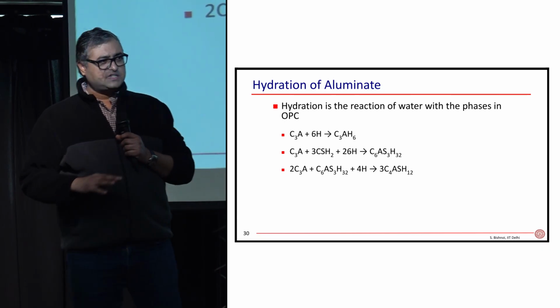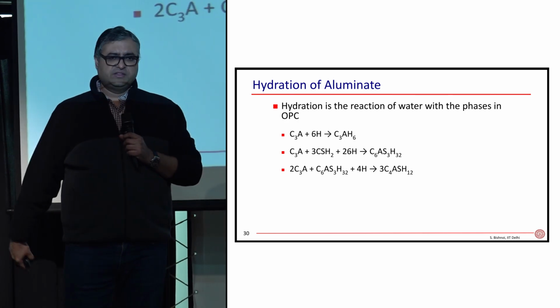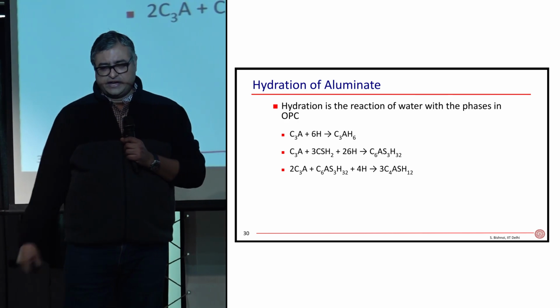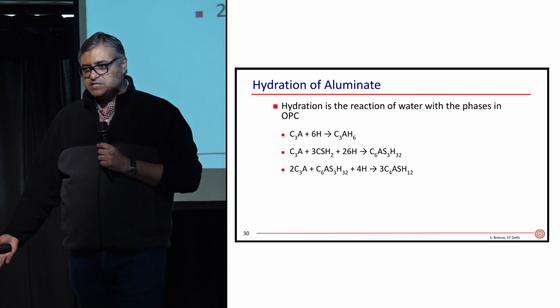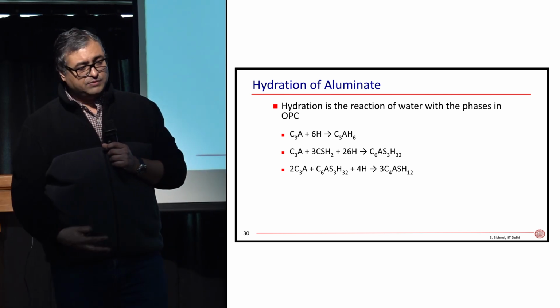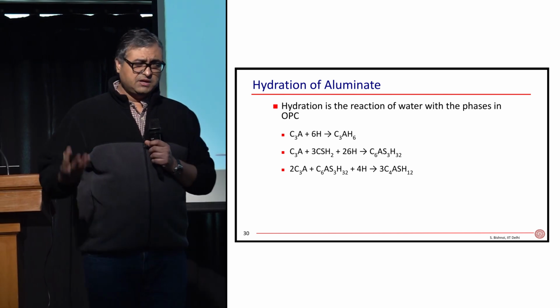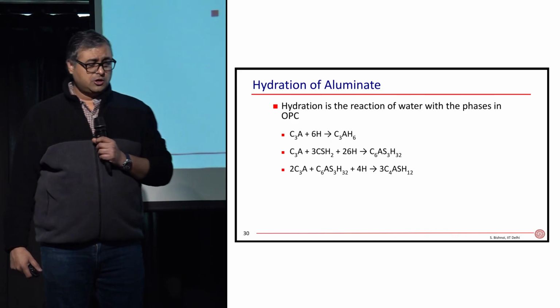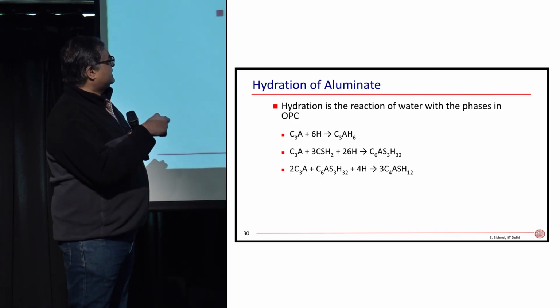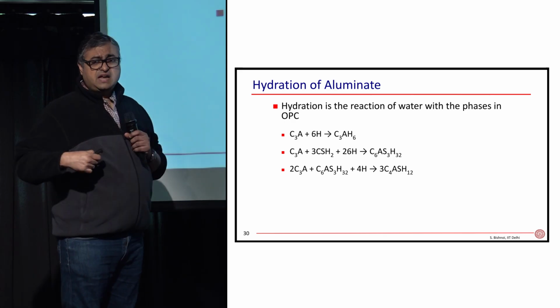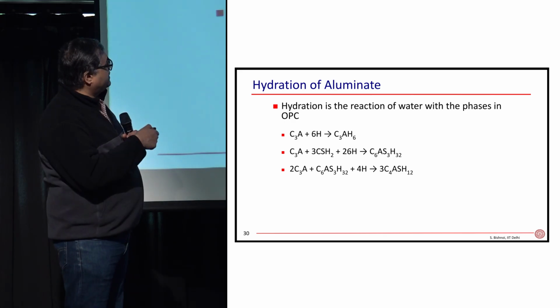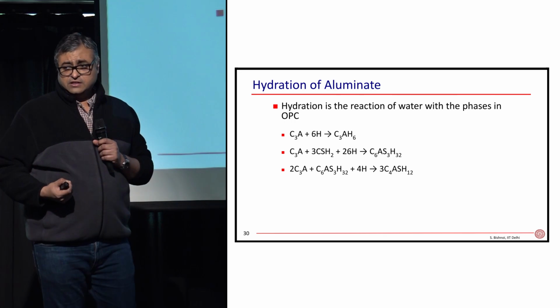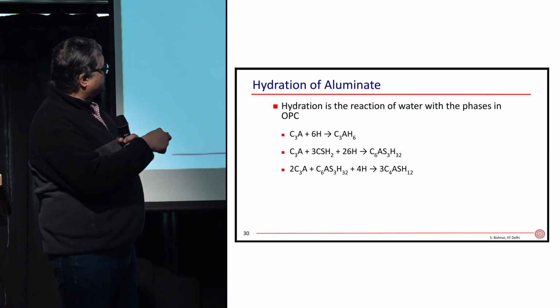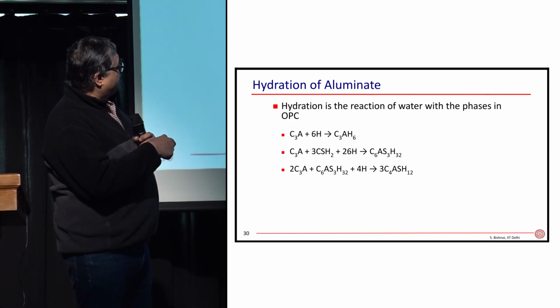People say that some of the sulfate goes and adsorbs on the surface of the cement particles, slows down their dissolution. I'm not 100% sure because, once again, there's something for which we don't have any evidence. That's something we'll continue arguing about to justify our jobs. But when C3A finally does start to dissolve, it finds gypsum in the solution. Sorry, this should be S bar once again. I don't know where the bars went, but this should be S bar.